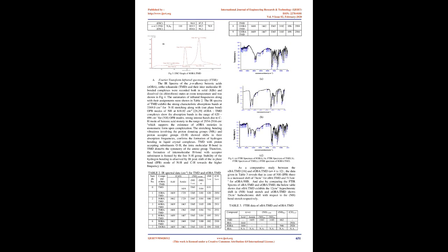Compounds are taken individually and mixed in the pyridine solvent, 20 ml. Thus the naturally existing dimeric forms of nOBA compounds with complementary hydrogen bond are converted into the monomeric form. Now the two solutions are mixed and kept under constant stirring at 80 C for 4 hours. Then most of the pyridine is removed by vacuum distillation process.